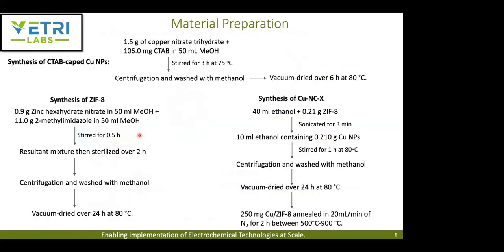And in this slide, we can go over how each of these materials is synthesized. First they synthesize the CTAB-capped copper nanoparticles by mixing 1.5 grams of copper nitrate trihydrate with 106 milligrams of CTAB in methanol as solvent, stirred for 3 hours. Then they centrifuged it, and the precipitate was washed with methanol and vacuum dried for about 6 hours at 80 degrees Celsius.